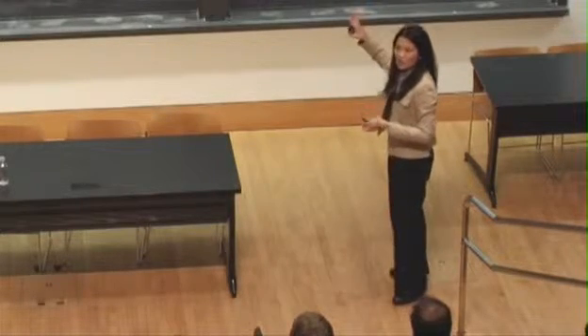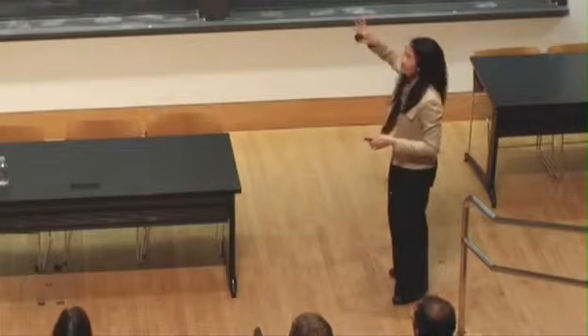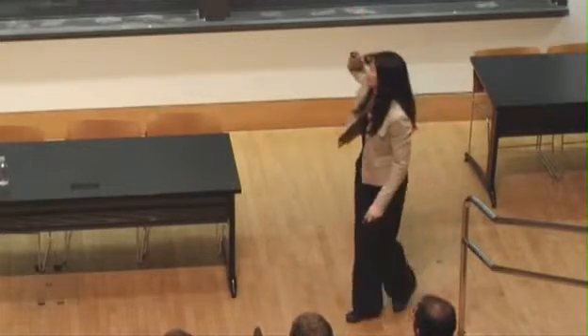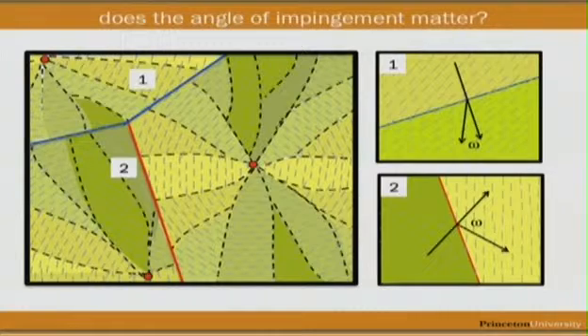So I'm showing you a cartoon, but there was a lot of X-ray work that's gone on for us to figure out what this cartoon looks like. So this cartoon shows a spherulite, or 3 spherulites. These are the nucleating points of the spherulites. And when you expose them to solvent vapor, they grow. And they grow in such a way that the molecules are always edge-on, okay? And the molecules basically steadily march along in the radial direction, okay? So that's what the molecules look like. So this is the pi stacking direction, okay? It goes radially outwards. So the molecules grow until they meet at a boundary.